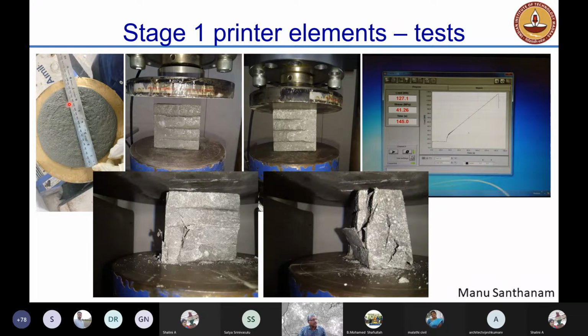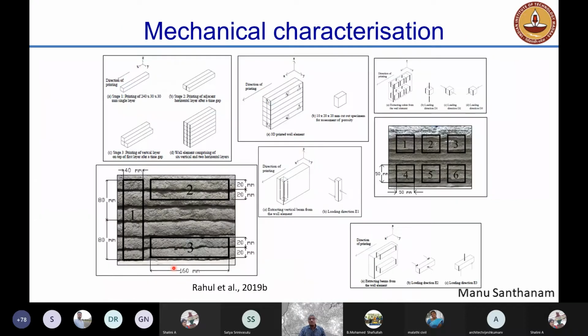But with respect to mechanical characteristics, here there's a 4-layered element that is being loaded in progression, and you can see it's a fairly good failure because the material is cracking properly and it's not going through the interface. Okay. Nevertheless, it's important to establish interfacial strength, because of which we went to a much more detailed scheme of characterization where we actually printed such elements which had multiple layers in both directions. And then we extracted samples from these layers. Cubical specimens as well as prismatic specimens were cut out from these layers and then tested to establish the proper material characteristics and the effect of the interface that was there between the layers.